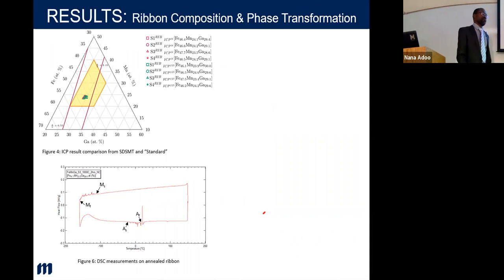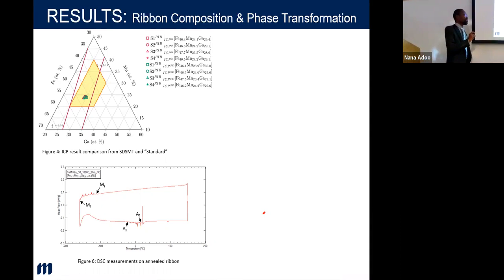Now, to get these phase transformation data, it is not only by magnetic measurement devices. You can use a DSC, differential scanning calorimetry, which takes specific heat capacities of these phases and shows you the differences as you go along. From what I showed you in the square, you're looking for a start temperature where one phase begins and a finish temperature. The Ms and As denote the martensitic start and finish, and the austenitic start and finish temperatures.